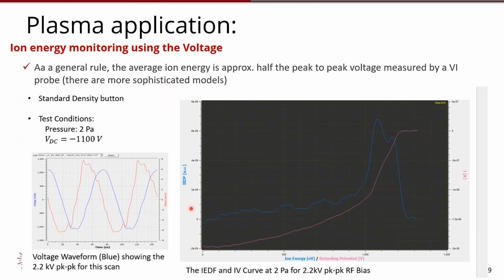Obviously, on the generator side, if the generator is working well, you have a perfect sine wave for the voltage and a perfect sine wave for the current, and there's zero phase between them, so they're completely overlapped. But on the plasma side, there's a larger phase difference, and you get these distortions in the waveform due to plasma emissions. If we don't run out of time, I will go into the physics of this and the applications of this. But that's a very simple thing. The voltage will give you the ion energy. Okay.